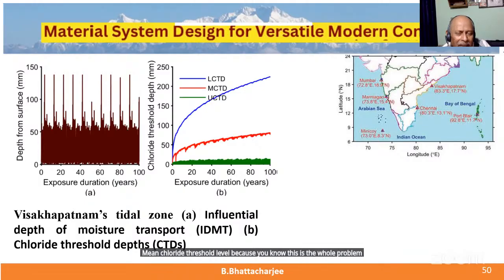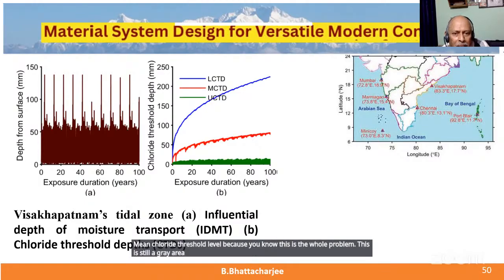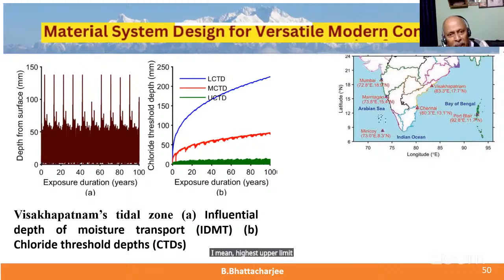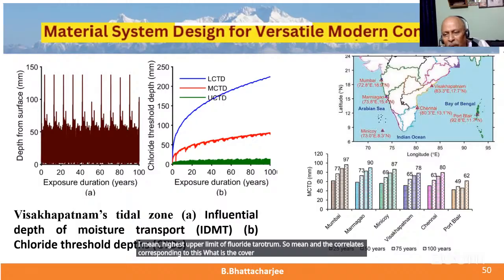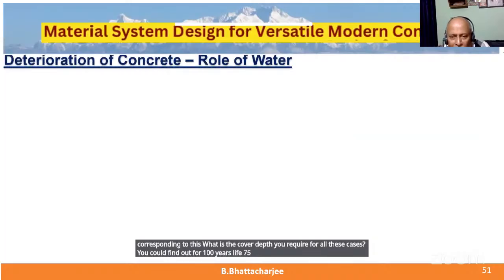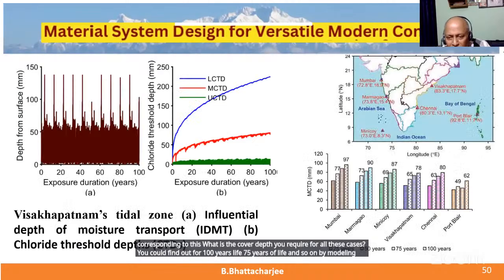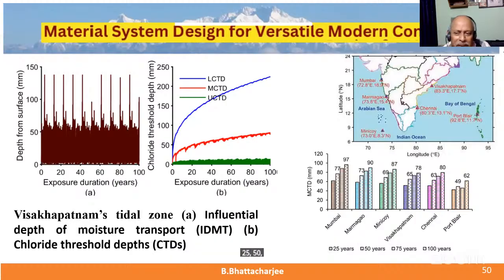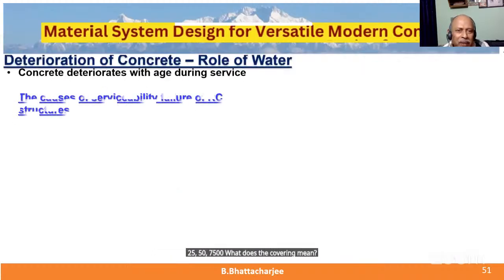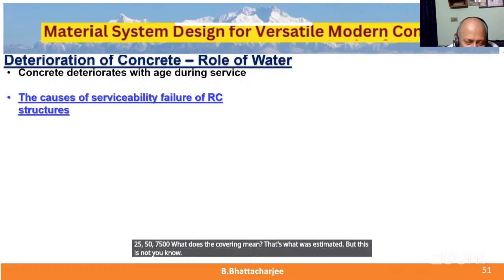This is still a gray area. Green is the lowest chloride threshold, and this is the highest upper limit of chloride threshold. So corresponding to the mean, what is the cover depth you require for all these cases? You could find out for 100 years life, 75 years of life, and so on by modeling. In this theoretical model, for 25, 50, 75, 100, what is the cover you need? That's what was estimated. But this is only theoretical estimation. Validating is not very easy in any one of these cases.